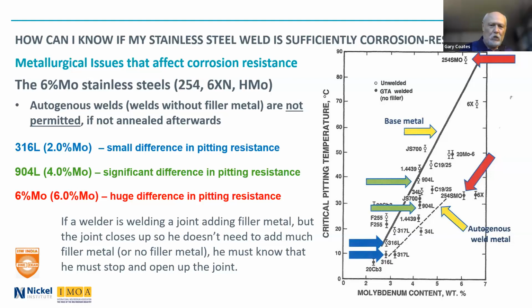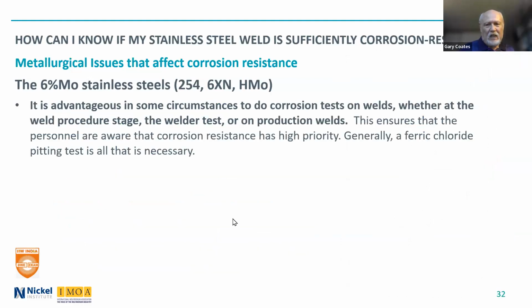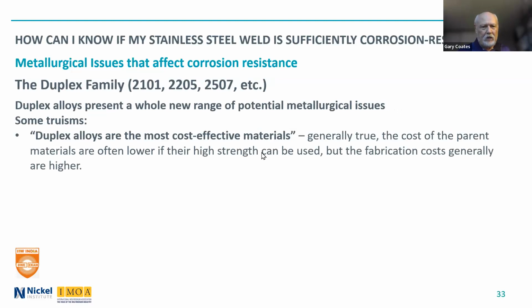So this is some training that the welder has to hear about, and it is possible to do weld tests. Often it is weld tests, the corrosion tests on welds. And it's important to show it to the welder. If you do an autogenous weld and you see how bad it is when you do it that way, that visual image may be more important. And some companies will specify the corrosion test on the weld procedure test, on the welder test to show the welder, and on production welds, just a standard one, just to make sure that people are following the procedure. And generally it's a 24-hour ferric chloride test. 40 degrees C is the temperature for most of the 6 moly alloys.